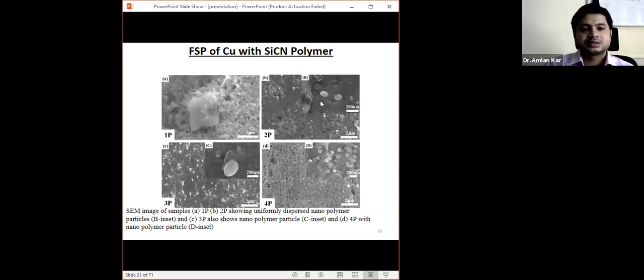And you can see the polymer particles after the processing. After the first pass and second pass, you can see some pores. In the figure, you can see the uniform dispersion of the polymer particles. Some are in the micrometer range, but many are small particles; you can see these are in the nanometer range. This is after the third pass, and this is after the fourth pass. If you take the polymer particle and process it, a nanocomposite can be obtained after the fourth pass, and we can also overcome the defect formation, defects in the sense of porosity.